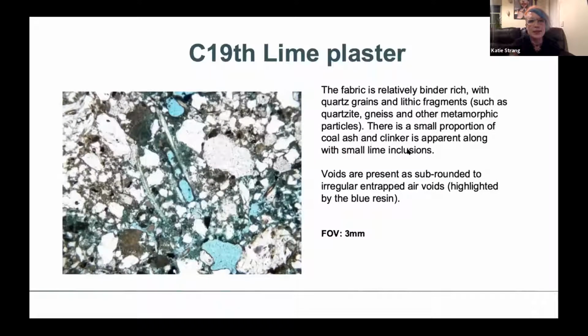So looking at some thin sections here, this is a general overview of your lime binder. Again, you've got your blue space, which is filled up with blue resin, and the fabric looks quite binder rich. All this brown material here is the binder, and this is all your aggregate particles here, which is mostly quartz and other material, metamorphic rock as well. And there are some small lime inclusions in here too, and a lot of voiding.